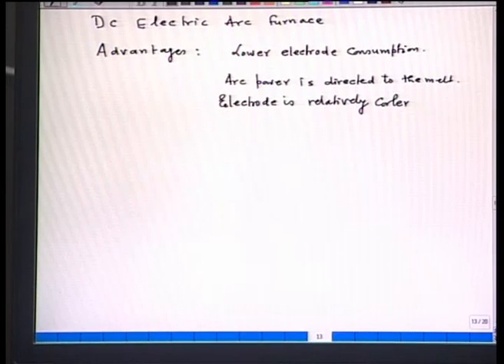Now, how is arc power directed to the melt when we compare to the ACEF? ACEF generates an electric arc because scrap acts as an anode. So, the heat transfer occurs from the arc to the melt. In case of DCEF, you have one anode that is embedded at the bottom and one graphite electrode at the top. So, the current flows in the metal because of the cathode and anode. So, arc power is better directed to the melt as compared to that of ACEF. Therefore, the electricity utilization is much better in case of DCEF.